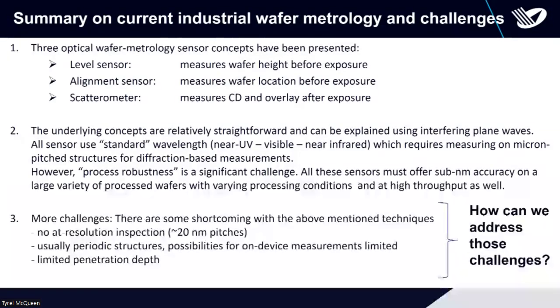What is very much pushed now is simply shorter wavelengths. Shorter wavelengths help with a lot of these things. If you make the wavelength short enough, you diffract from a 20-nanometer structure. So we're talking about soft X-rays. If you work with this, you have diffraction, and you can in principle do a full field imaging experiment at this wavelength. It will take very long, but it's possible.